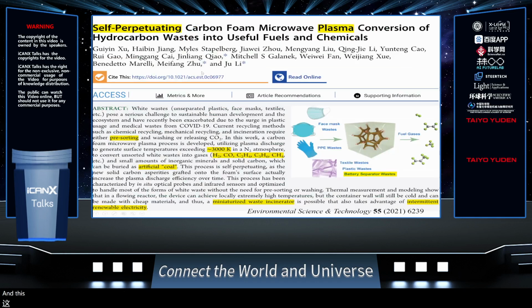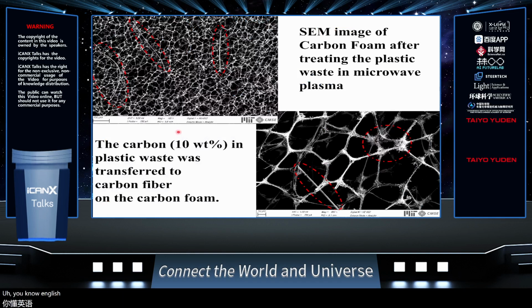And this is in collaboration with Dr. Qing-Jie Li and Professor Meifang Zhu, where we have shown you can convert a whole range of waste organic matter into useful gases. And the last 10% of the plastic material is actually converted to carbon itself. So you have some kind of self-reinforcing foam, and in fact, the plasma discharge efficiency improves with the 10% solid carbon in the plastic waste. So we envision this could be a self-perpetuating process.